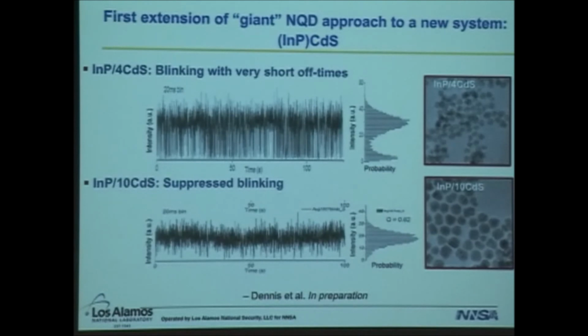The dirty secret behind these is that this is, we think, a real type 2 system, largely because the lifetimes are very long, a few hundred nanoseconds. And we're getting this very dramatic red shifting of the emission maximum out into the infrared, beyond the bulk band gap of indium phosphide. You clearly have a CT kind of state going on, and so that makes these fairly dim. The quantum yields are not awesome for this system, which is why it's such a torture to get this data, but it's still interesting.